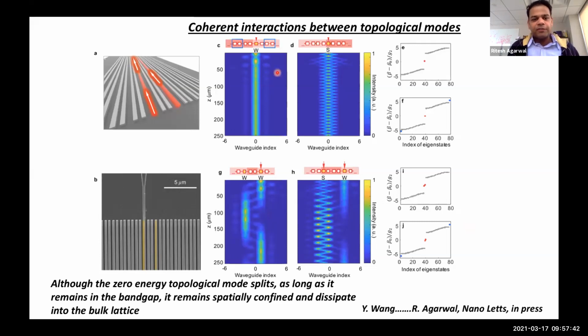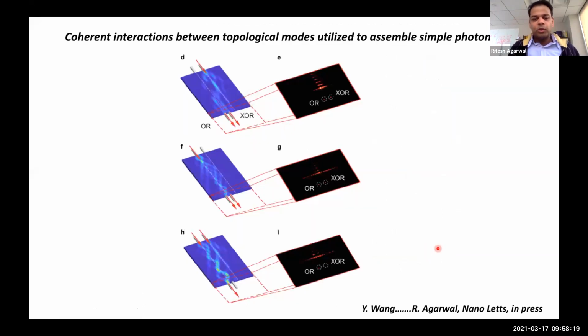We've taken the first step and shown in the photonic regime that if you have two different topological photonic modes, and we are extending this to the polaritonic regime, these two topological channels interact, but as long as the two modes are in the photonic band gap regime, one can confine excitations only in these topological modes, and backscattering is less. It's not zero because, of course, it's not purely topological, but still, there is no mode to scatter to. There are no modes here, so backscattering is strongly suppressed, and we've used this to make topological logic gates in the photonic regime, and the idea is to extend this to the polaritonic regime.